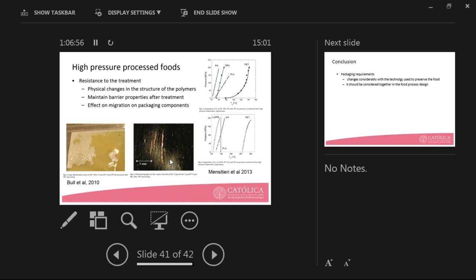Another requirement is the resistance to the treatment. We know that physical changes in the structure of the polymers that are typically used may occur. And I show you here several pictures collected from the bibliography, and we can see in this case delamination, that's the separation of the different layers of a material, and we have here some flex cracks of aluminum foil from PET laminate, which can compromise the barrier properties after the treatment.